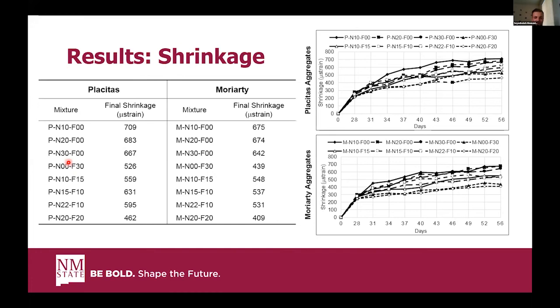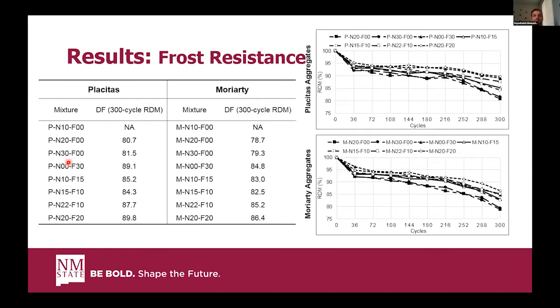It's correct that both of them are acceptable because they are less than 670 microstrain or something like this. But you should be careful when you're using natural pozzolan in an area where shrinkage is important, because we know that the shrinkage can be more than the mixture with 30% fly ash.